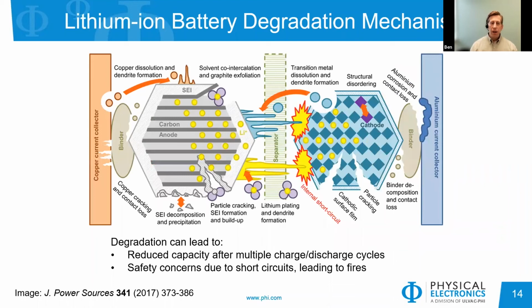And for a lithium-ion battery, there are a lot of things that can happen. We have chemistry happening as the lithium moves in and out of these electrodes. There are reactions happening at the surfaces where it's breaking down the electrolyte material. The lithium, as it moves in, can cause swelling of the electrodes, and so there's mechanical stresses happening in there. And as those happen, we might start getting electrochemical migration of, say, lithium dendrites that can then move across and short circuit the battery. And so we really just need to understand, at the very surface level, what reactions are happening. With these degradation mechanisms, we can see reduced capacities and possible safety concerns.